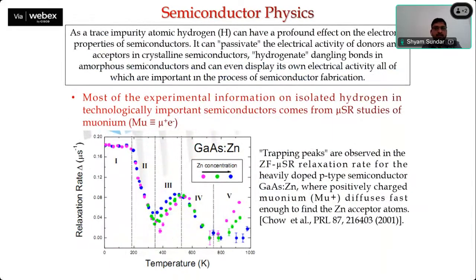Another is in the semiconductor physics. As a trace impurity, atomic hydrogen can have a profound effect on the electronic properties in semiconductor materials, and it can passivate the electrical activity of donors and acceptors in the crystalline semiconductors, dangling bonds in the amorphous semiconductor, and can even display its own electrical activity, all of which are important in the process of semiconductor fabrication. So basically, if you want to understand how the hydrogen is going to affect its properties, you can basically study this using the muon MUSR technique.